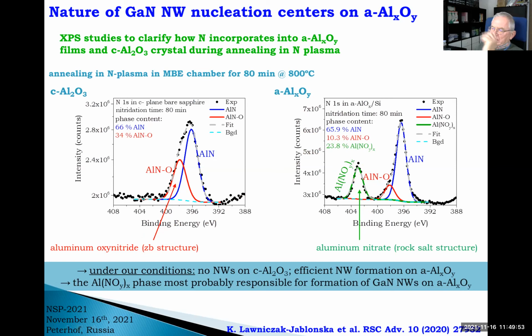So having this, we know from our experiments that on crystalline substrates, we do not have nanowires under our growth conditions, while on amorphous aluminum oxide, these nanowires appear. So this gives us a hint that most probably this compound created during nitridation of aluminum oxide may act as a heterogeneous nucleation center. Of course, right now this process is not finished. We are at the stage of correlating quantitative results of nucleation kinetics with the concentration of these phases. But okay, this is a hint that something is going on, and this phase must be considered.